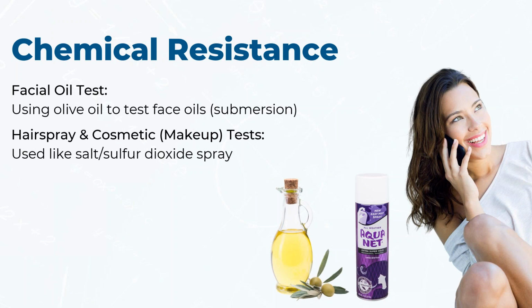The other tests that consumer electronics are big on are hair and cosmetics. Again, this is just like a salt or sulfur dioxide spray in a chamber. You mount your optics in a sealed chamber and introduce gas with hairspray and cosmetic chemistries. Then after a set period of time, you pull it out of the chamber and inspect it for transmission loss, adhesion loss, or anything that may have interacted with the coating chemistries and created weaknesses.